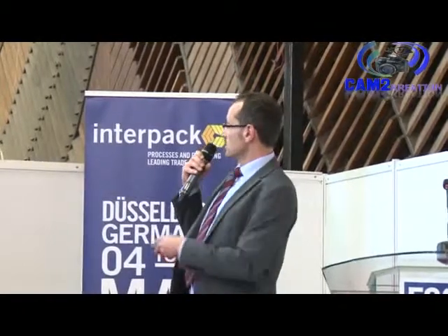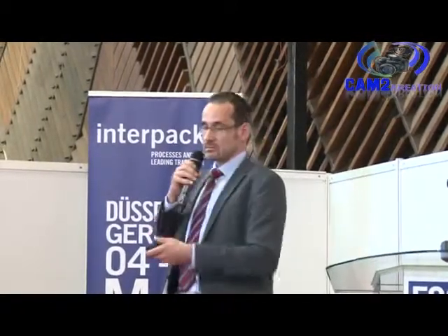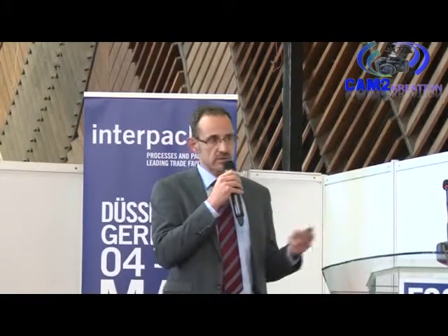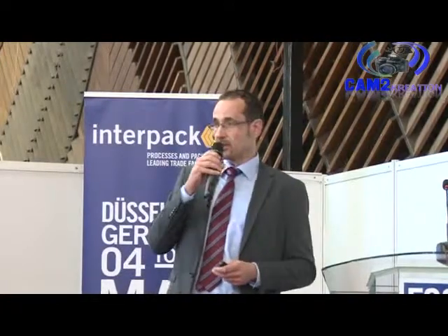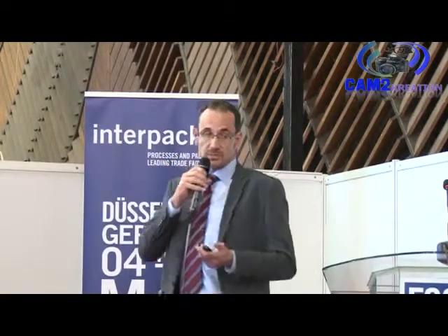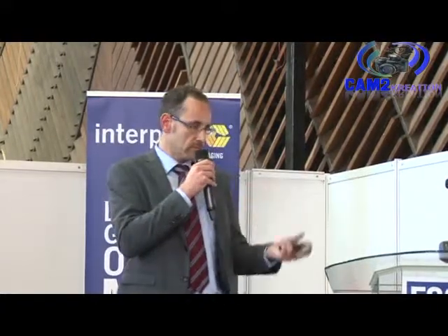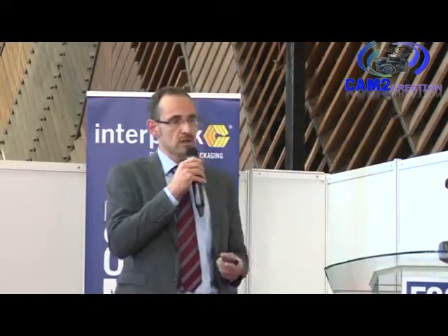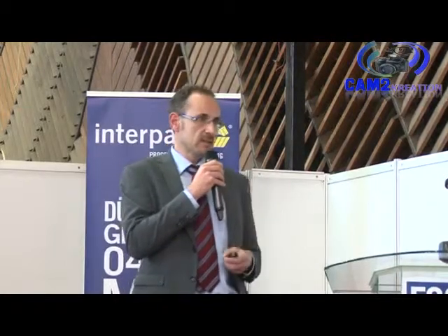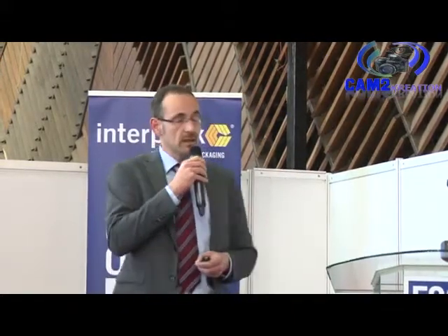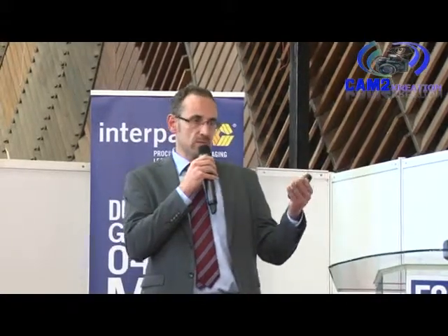In terms of the red one, the temperature resistance, it has a relatively high melting point, depending on the type. It goes from 190 degrees melting point up to 280, depending on the nylon type. This especially gives you the properties for post-treatment. If you have a flexible packaging, for example, that you want to bring to retort, you have to have a polymer which can withstand this retort process. It also helps you much in terms of sealing. If you put the nylon as the outside layer, you can seal with much higher sealing temperatures, which gives you an increase of filling line speed.